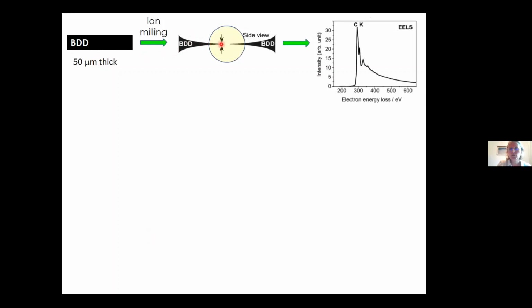And then what we do is we thin by an ion polishing technique. So we'll have a region, and we end up going through the BDD in the center to really prove that the regions around the center hole are electron beam transparent. And one of the nice things with TEM is you have the ability to do things like electron energy loss spectroscopy. So you can get spectroscopic information on the metal ion identity, the oxidation state. You can get diffraction information at very, very high resolution. So we can use this EEL spectrum to calculate the exact thickness of our electron beam transparent diamond.